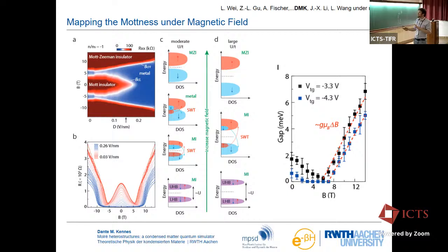And from just the measurements of the resistance, you can show that it's not this regime, which is proposed usually, where you have a very large U, you have well-formed upper and lower Hubbard bands, and then you basically already have frozen out the charge degree of freedom, and you have, let's say, an antiferromagnetic state, and your small magnetic fields can just flip all the little spins up because you only have a very small exchange energy T squared divided by U.